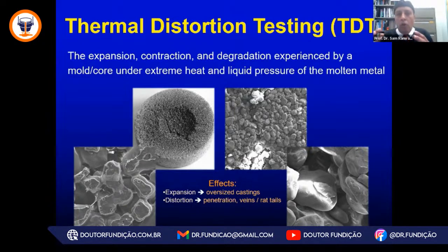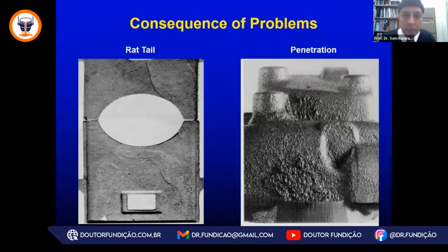So the thermomechanical test of thermal distortion testing allows us to evidence expansions that can be depicted in oversized castings, as well as distortion or the displacement of the mold walls, the dilation of the mold wall, or the sagging of the mold wall, causing bending or thermal shock to that sand binder system that can lead to penetration, veins, or rat tails as a defect. In case you need to remember what those defects look like, I am showing on the left a rat tail or a vein.